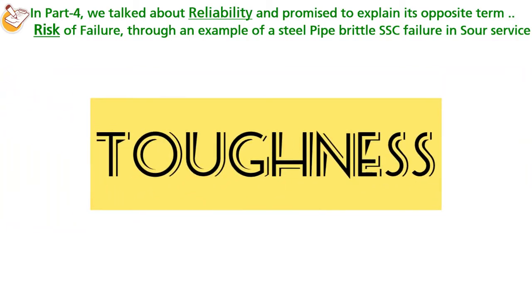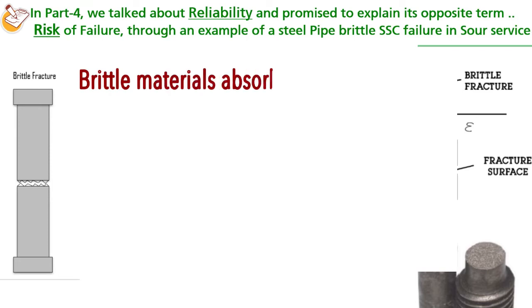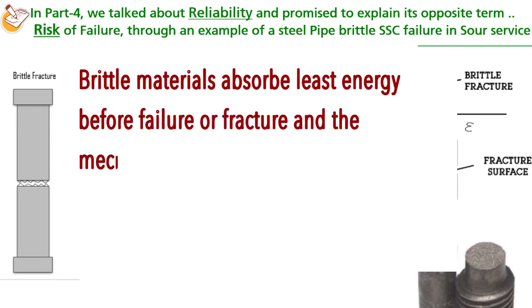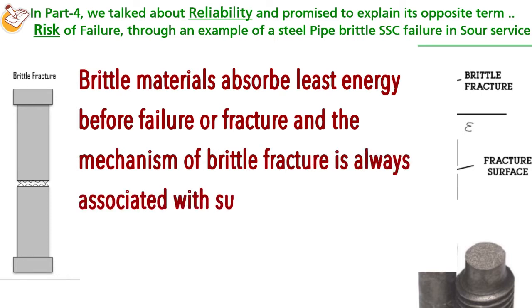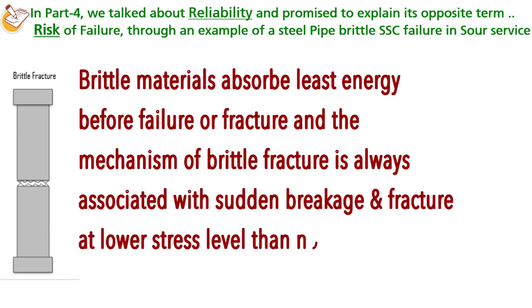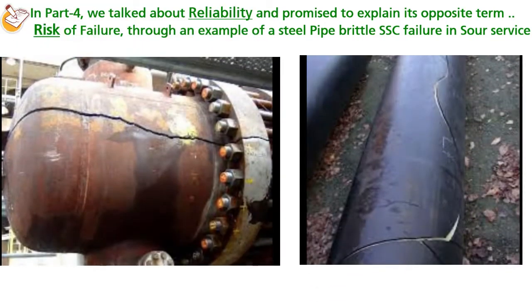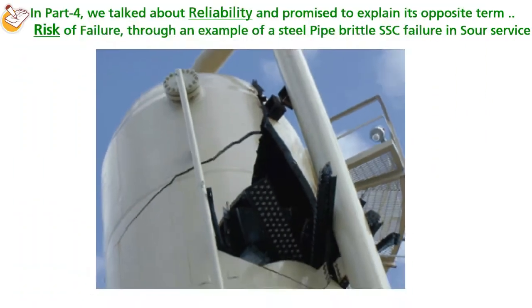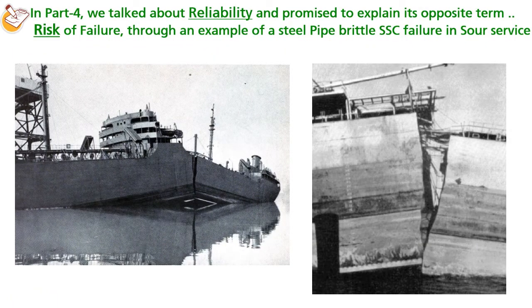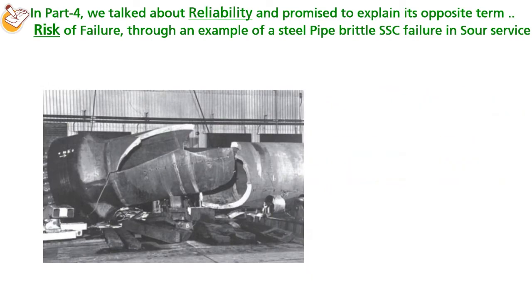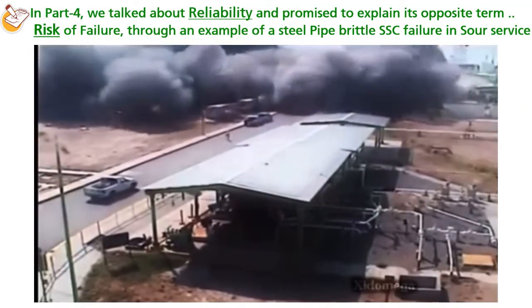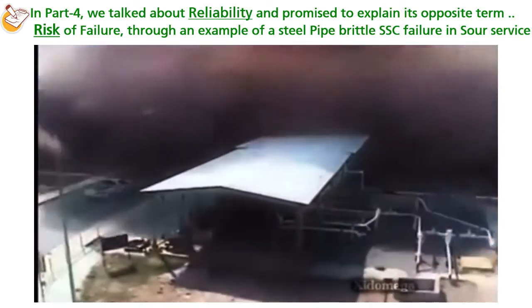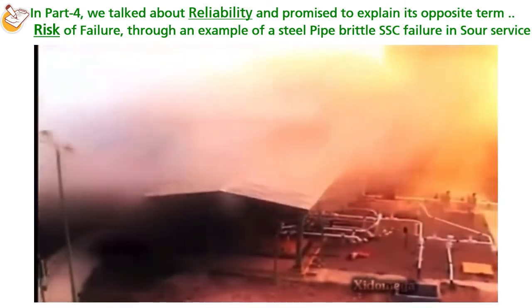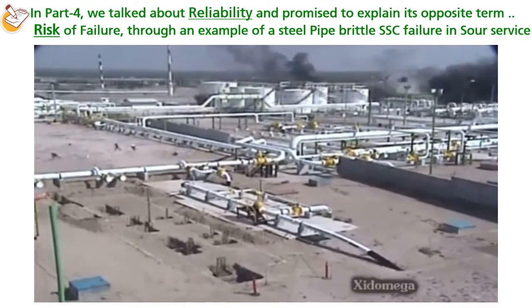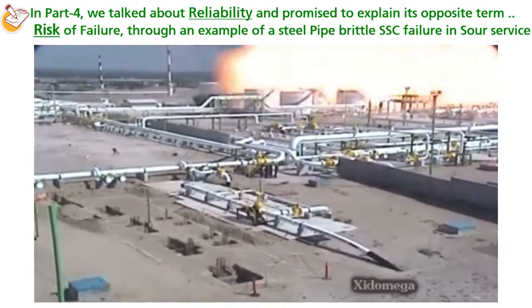Toughness is an important property when we talk about brittle fracture, since brittle materials absorb the least energy before failure or fracture. The mechanism of brittle fracture is always associated with sudden breakage at a lower stress level than normal, and this sudden nature of the failure without any visible warning signs of deformation results in losing the chance to take any preventive actions to avoid the failure and its catastrophic consequences. And just to know the impact of brittle fractures, in 2007 in China alone, 257 cases of special equipment accidents occurred, which caused 325 deaths and 285 injuries, and more than half of these accidents were caused by brittle fracture.